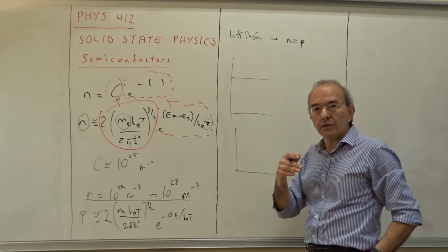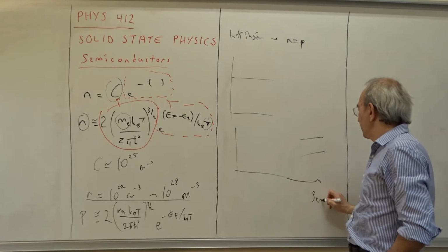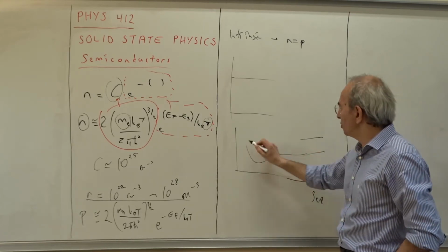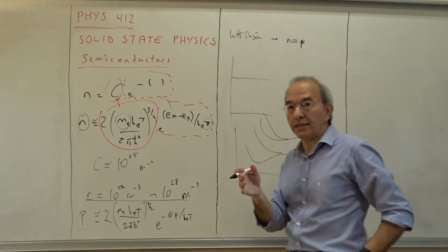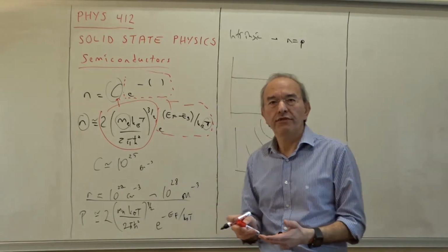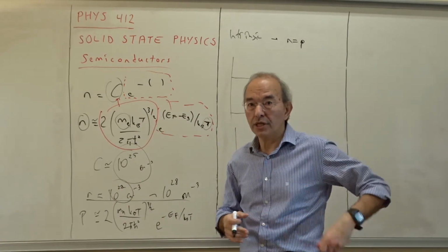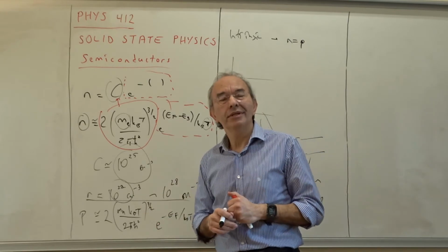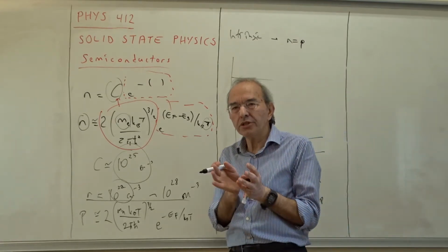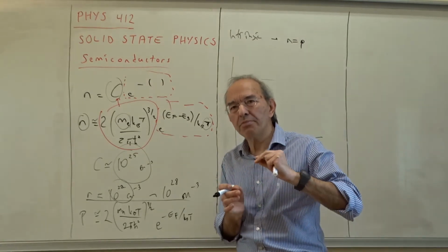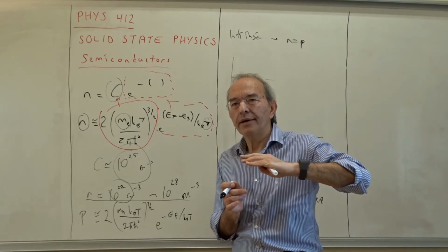If we have only two atoms, these separate energy levels at very large separations now split into two, and this is also split into two, etc. But if we have n atoms, and in general, for a real crystal, of course, n is on the order of those very large numbers, very large concentrations, 10 to 22, for instance, per cubic centimeter, then these are just some bands. So they split into very finely separated, quite near each other, energy levels.